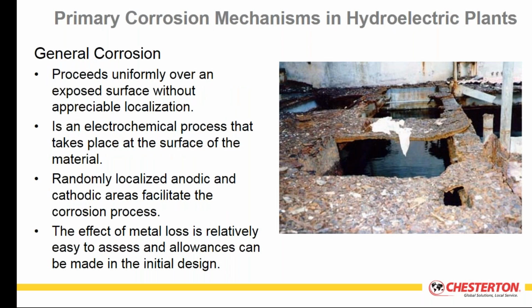You'll also see throughout the plant what we call general corrosion. This is the exact opposite of pitting corrosion. It's much more uniform across the surface because areas across the metal are becoming anodic and cathodic, constantly changing. The rate of attack is much more measured and progressively slow. It tends to occur uniformly or generally across the entire surface, not localized.